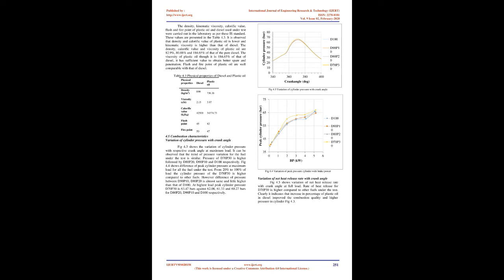It can be seen that there are 8 major peaks. Using the characteristic infrared absorption bands of functional groups, the class of compounds, their intensity, and nature of bonds are determined. Table 4.2 shows details of the compounds and their characteristics pertaining to the peaks observed in the FTIR analysis. The plastic oil sample consists of aromatics, alkenes, alkanes and alkyls, and carboxylic acids. The major peak is assigned to the carboxylic acid.